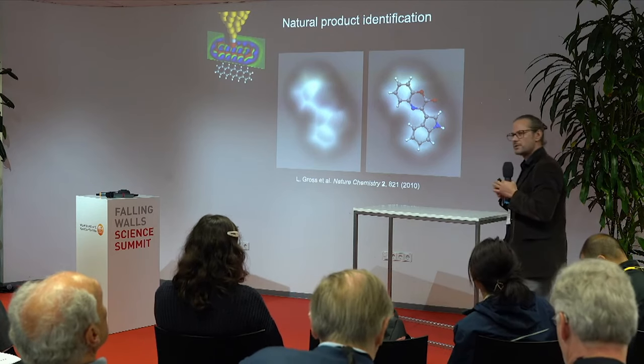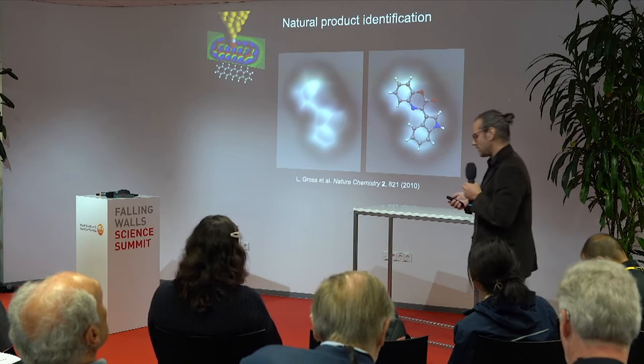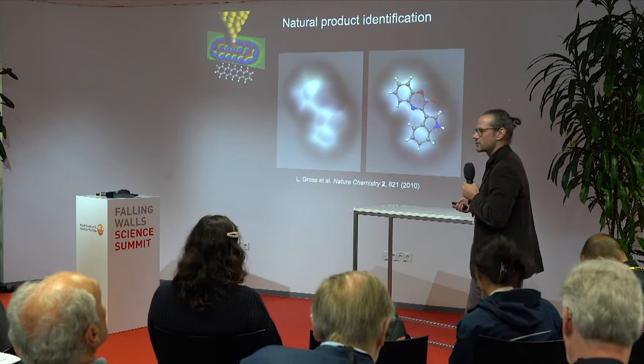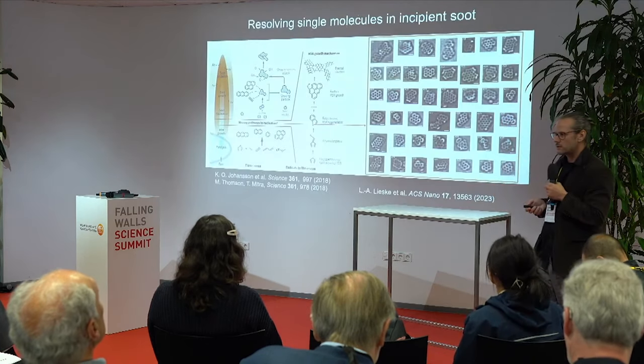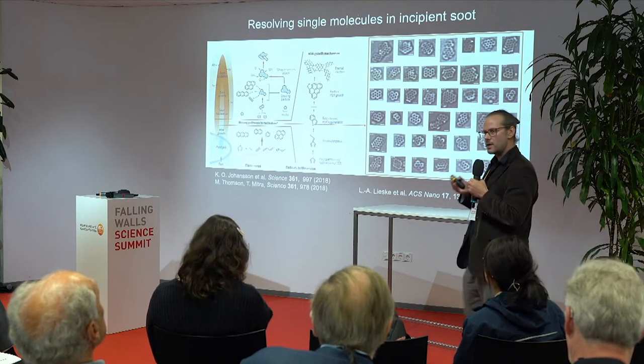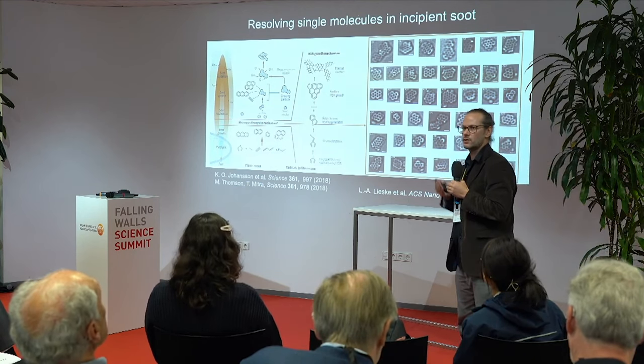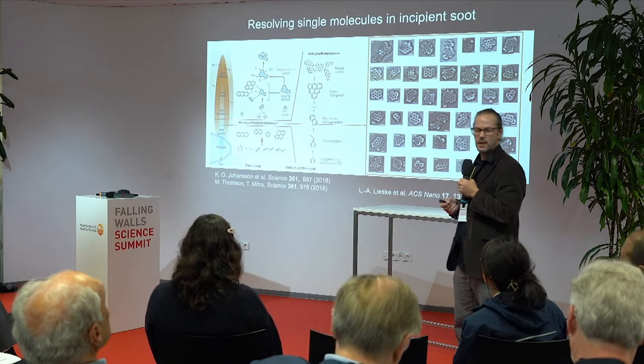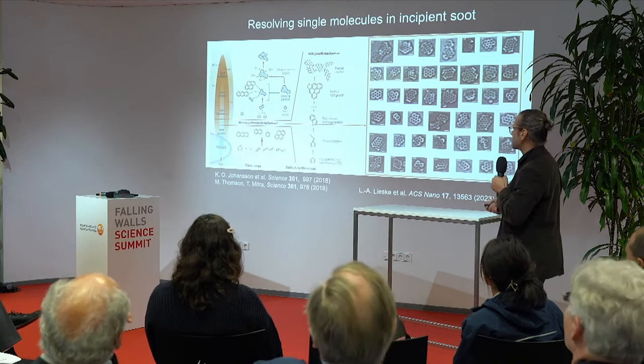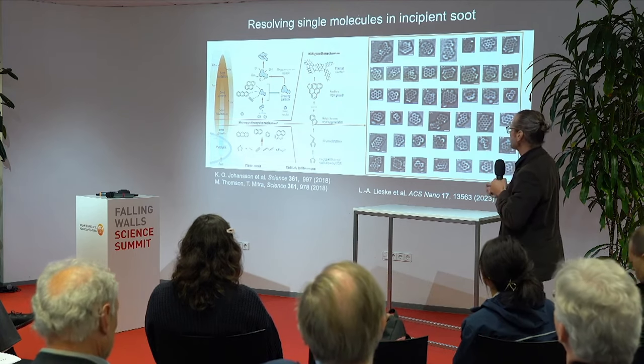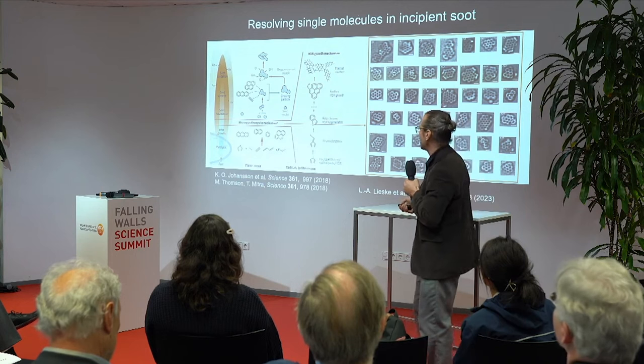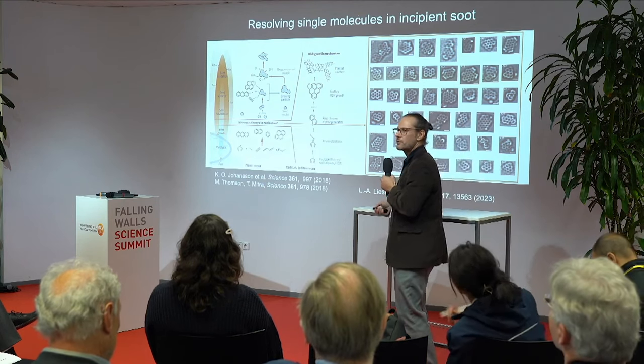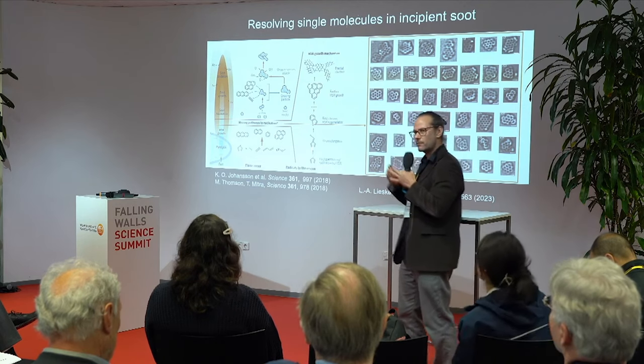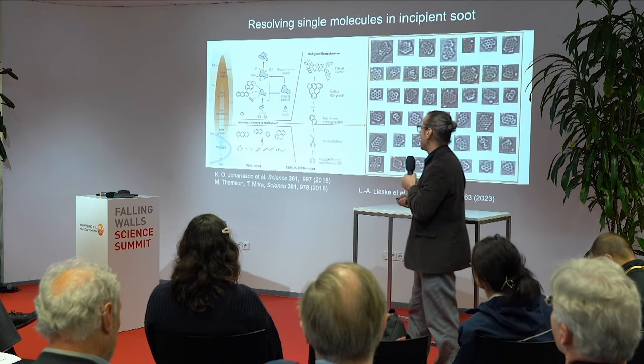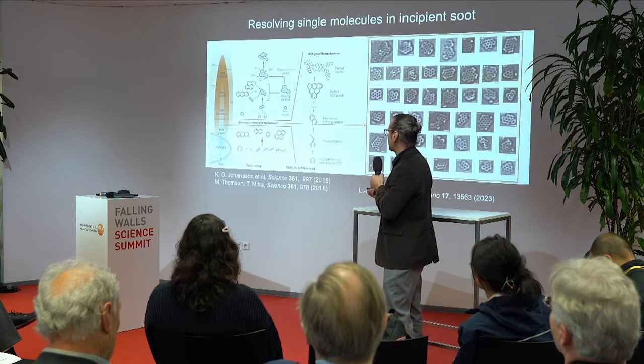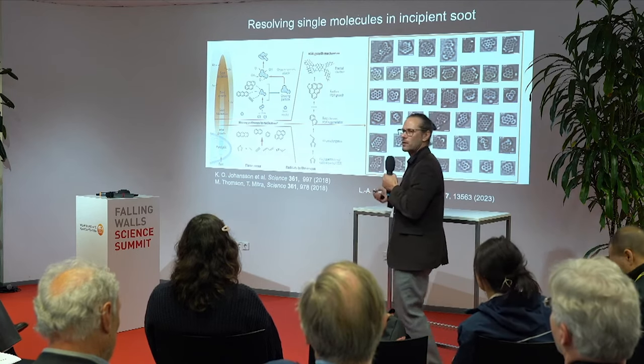But if you have a substance that has very many different molecules, then these averaging techniques have a challenge to assign the different structures. And now here comes our unique capability, in that we can assign a molecule based on a single molecule. So if we have a mixture of molecules, we can study this mixture one by one. And here we did this in soot. So these are all AFM images. On the left-hand side, you see the question that we tried to address. This is how soot particles form in the flame of a combustion engine, and then later they form fine dust and soot, which is not good for health. What was missing, basically, was how do these planar aromatics aggregate and form larger clusters?